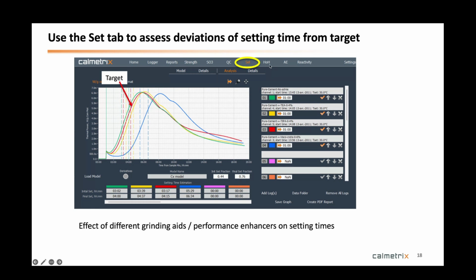So for setting time, for example, here you have a target setting time, and you could think about this actually as a case where you use different grinding aids or performance enhancers, and you want to look at how it affects the quality of your cement when you use one versus the other. Then you have a certain target, and you can easily assess how other dosages and how other types of grinding aids that are supposed to be equivalent will affect the setting time.